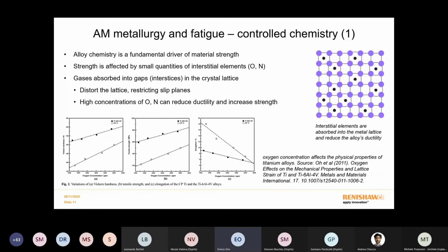Looking at the defects that can arise from the additive manufacturing process, certainly an important point is about the chemistry. The alloys that we use are very well controlled in terms of oxygen and nitrogen content, and the reason for that is that, as you know, these interstitial elements can insert themselves inside the intermetallic matrix to generate distortions and modify the ductility and the performance of the material. In general terms, the insertion of interstitial elements will increase the ultimate tensile strength of the material and the hardness, and will reduce the elongation, so it will reduce the ductility of the material.